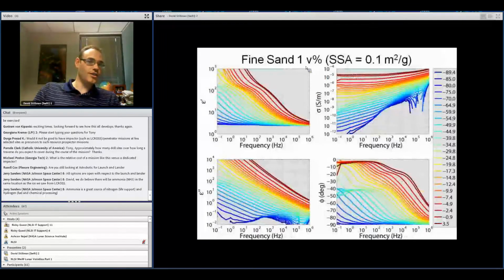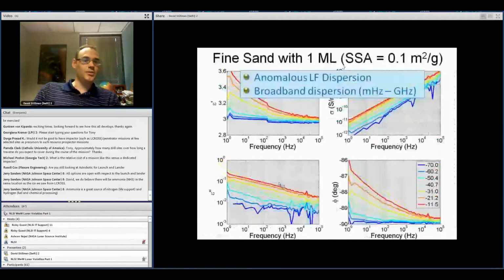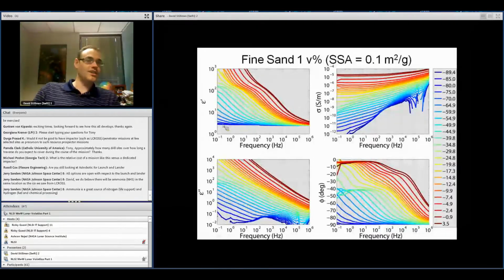Then if we add a little bit more water, one volume percent on the sand, you can see that things change drastically. So before we had a scale over here on the real permittivity of 3 to 3.6, and now we're going even above 1,000 here. So adding just a little bit of water with the adsorbed water gives you these really giant relaxations. And what you'll see over here is these temperatures are above freezing, so this relaxation isn't due to ice. This is actually due to adsorbed water.